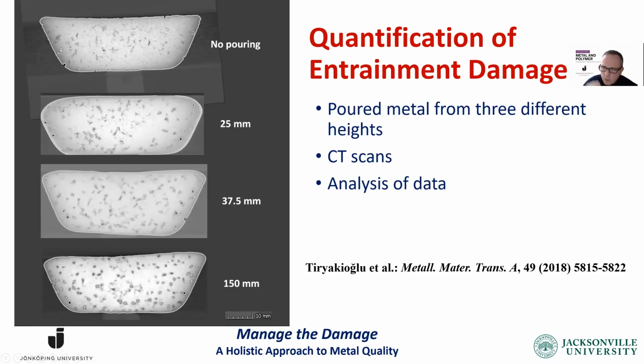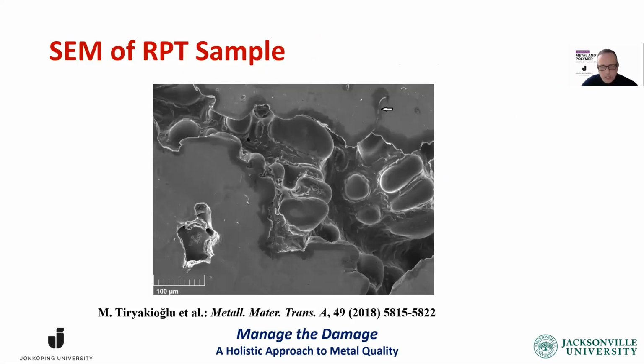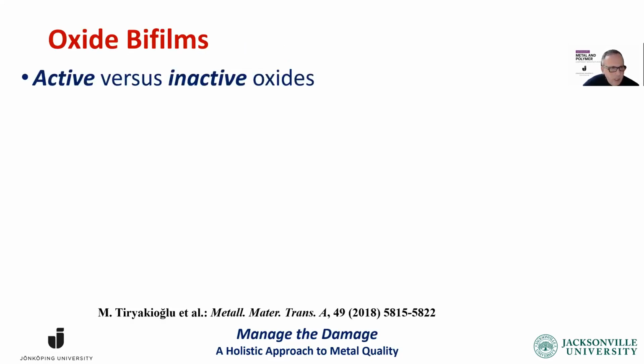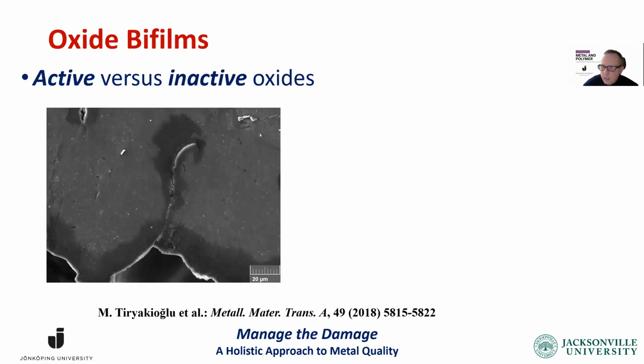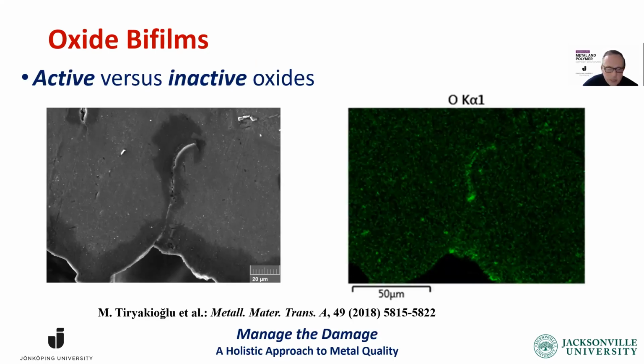specimen. This is the RPT specimen. We cut it into half, and we looked at it. Okay, you can see the huge pore expanded to, we thought, maximum limit. It cannot expand anymore. Then we saw this curious feature that you notice with the arrow. What is that curious feature? And we zoomed in, and then we did X-ray mapping, and it's oxygen. So that means there's a folded oxide there. There's a bifilm that's hiding there, and it couldn't open up. So the huge pore that we saw was only a part of the damage.